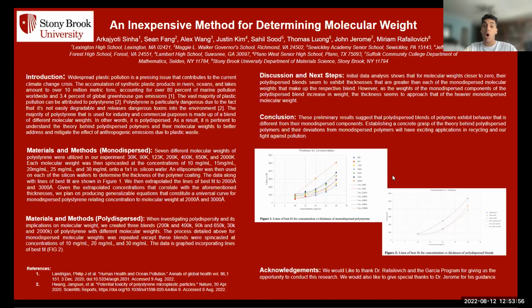We then moved on to polydispersed blends of polystyrene, which involved using different molecular weights in order to see the effects of varying molecular weights on the blend itself. So we blended 200K polystyrene with 400K polystyrene, 90K polystyrene with 650K polystyrene, and 30K polystyrene with 2000K polystyrene. These blends were spin casted at concentrations of 10 milligrams, 20 milligrams, and 30 milligrams per milliliter. And the resulting data, along with the respective lines of best fit, are graphed in figure 2.